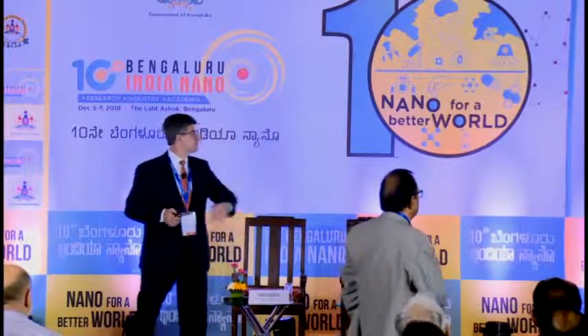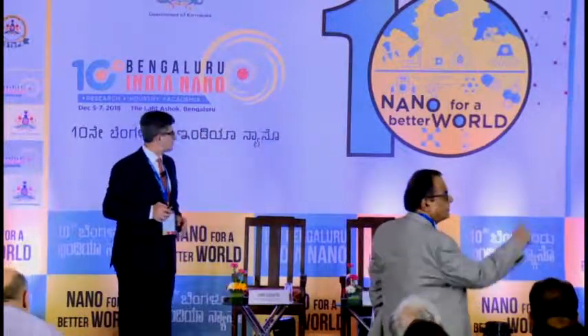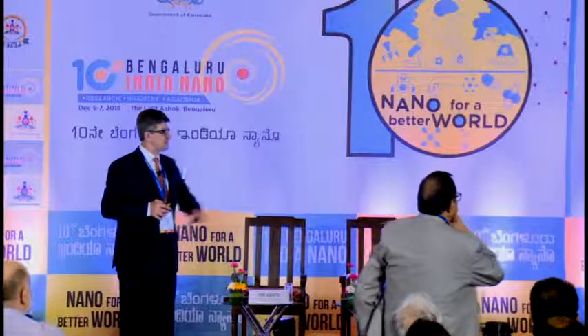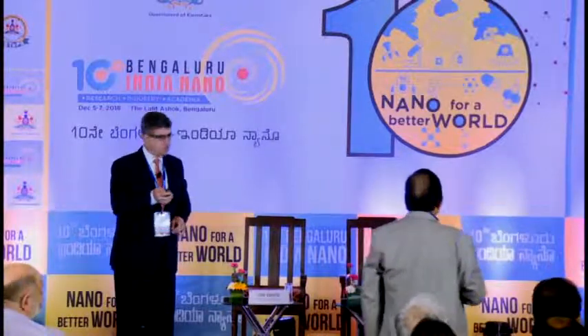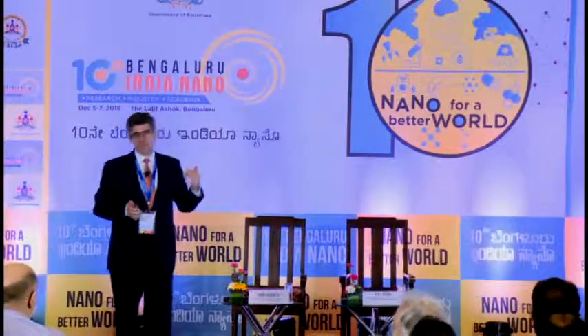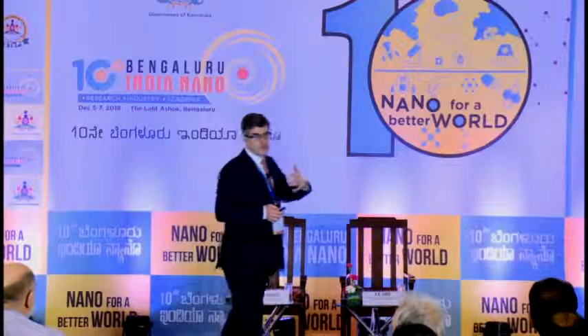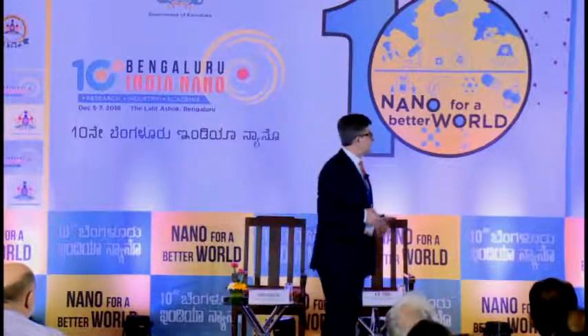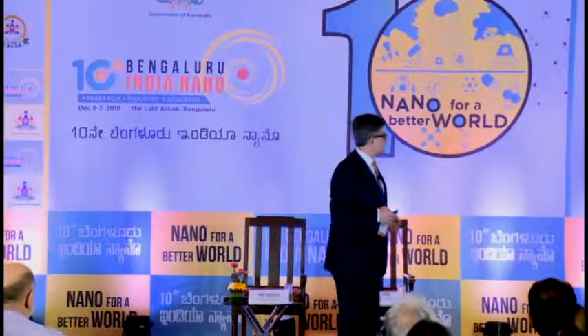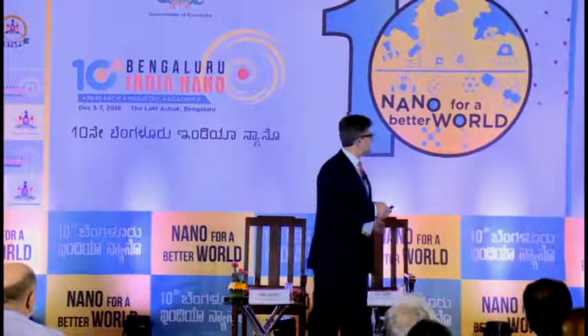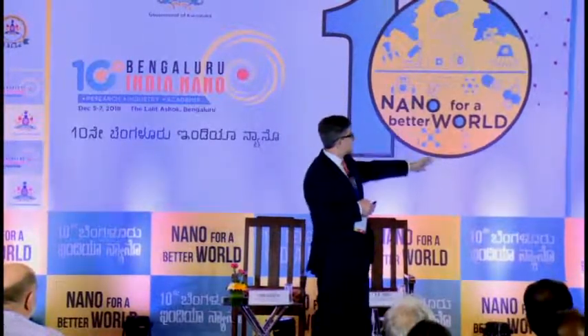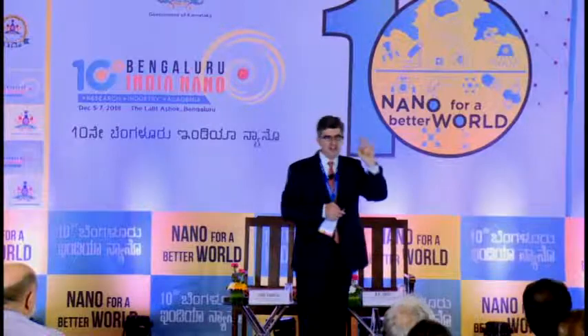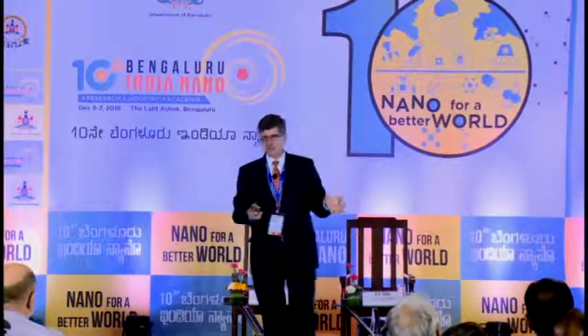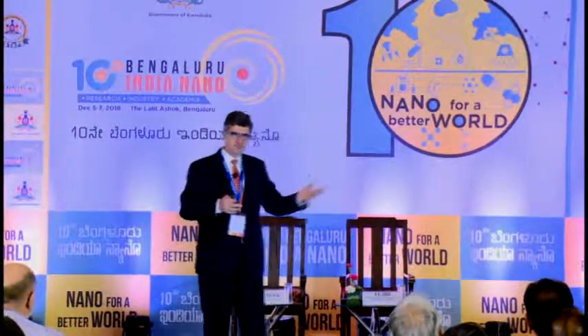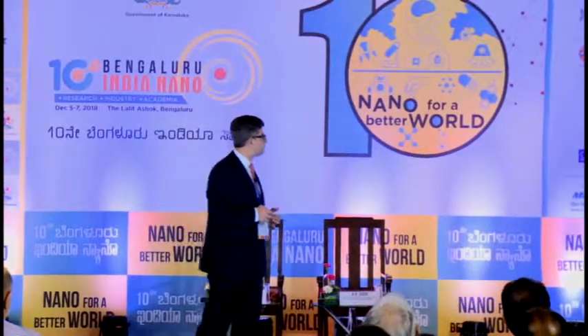You would see the synthesis process when we transferred it to the PC in the morning, it worked, but probably it has been lost maybe during transfer here. Anyway, what is important is that by simple spray coating this film, we can make, for example, this Drexel logo that my student Kathleen Maleski is holding here, or a letter-sized sheet, and this is actually a 5-micron thin paper, but you can make a paper airplane out of it. You can cut it into electrode films here.